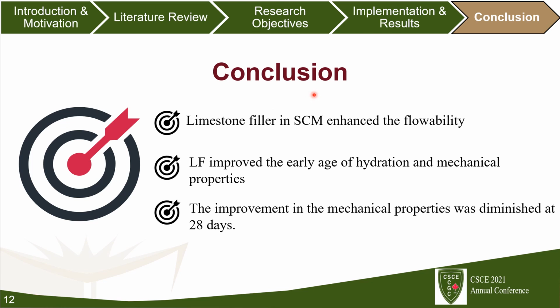So, to conclude, using limestone up to 15% replacement of cement is viable, and using limestone filler enhanced the flowability of the self-compacted mortar and the early age hydration and the mechanical properties. However, the improvement in the mechanical properties vanished after 28 days.